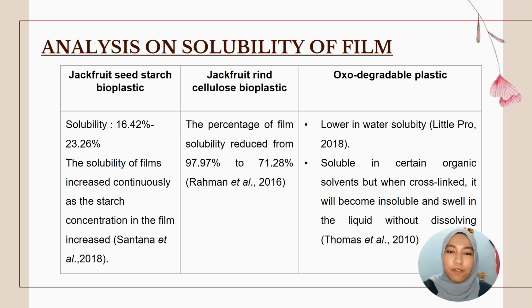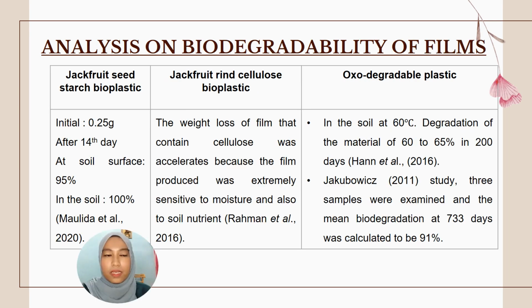Analysis on the solubility of film. For jackfruit seed starch bioplastic, the solubility is around 16.42% to 23.26%. The solubility of the film increased continuously as the starch concentration in the film increased. For the jackfruit rind cellulose bioplastic, the percentage of film solubility reduced from 97.97% to 71.28%, while oxo-degradable plastic has lower water solubility. It will dissolve in certain organic solvents, but when cross-linking happens, it becomes insoluble and swells in the liquid without dissolving. Next is the analysis on biodegradability of film.